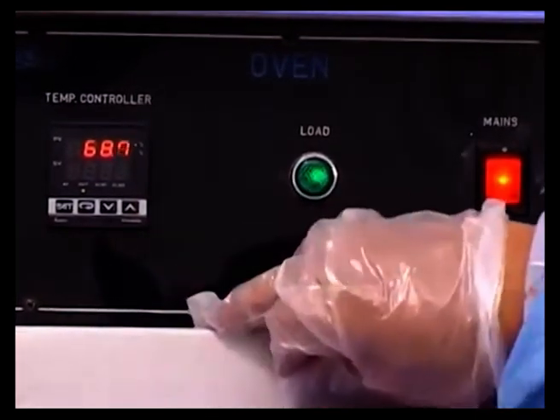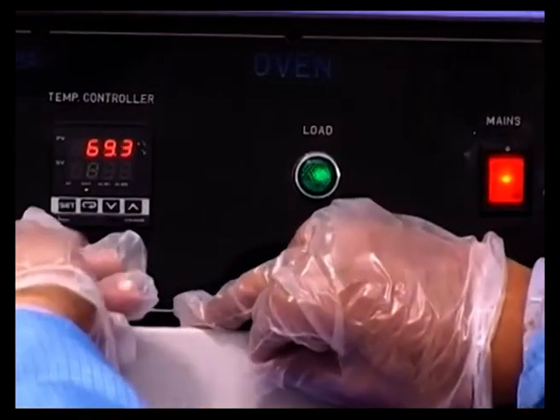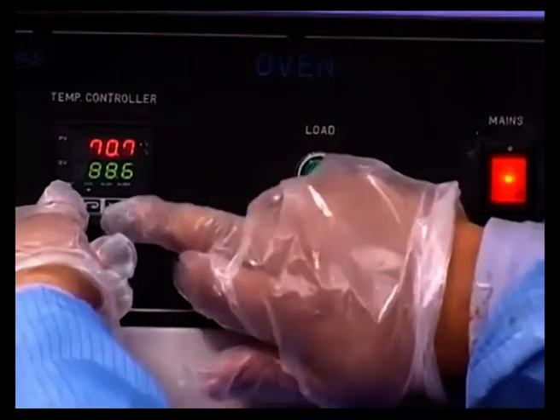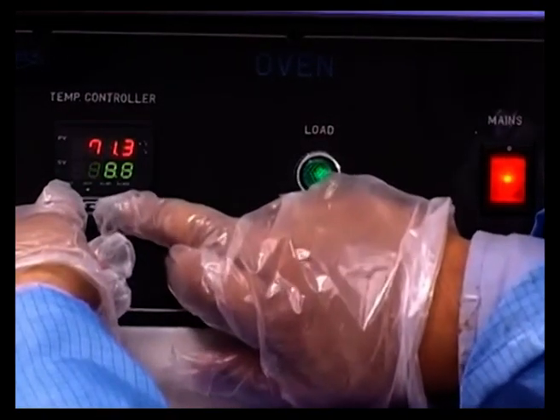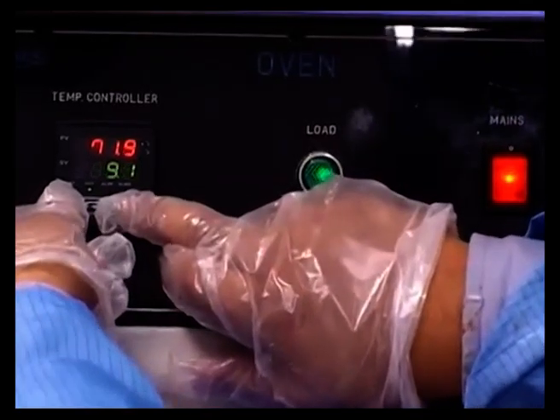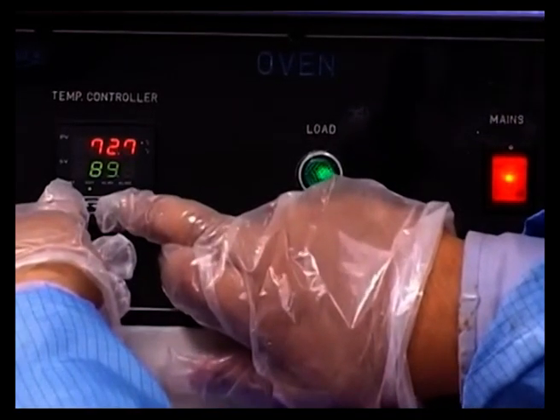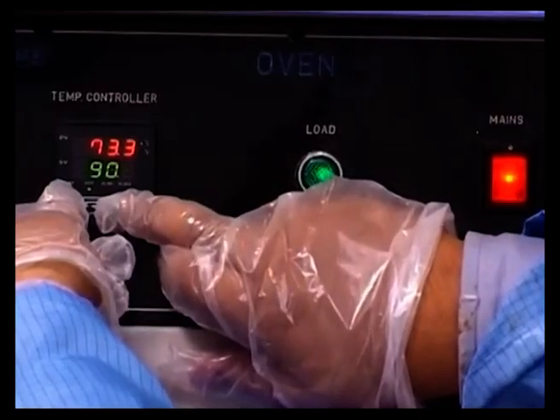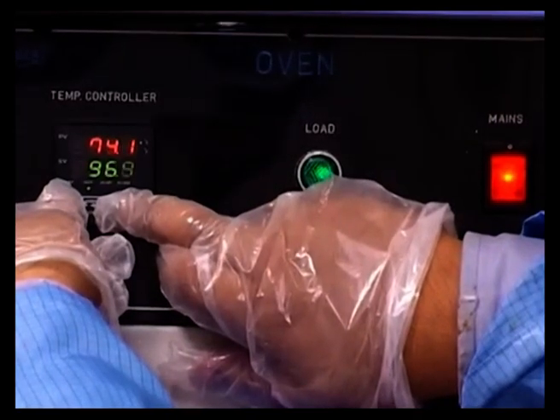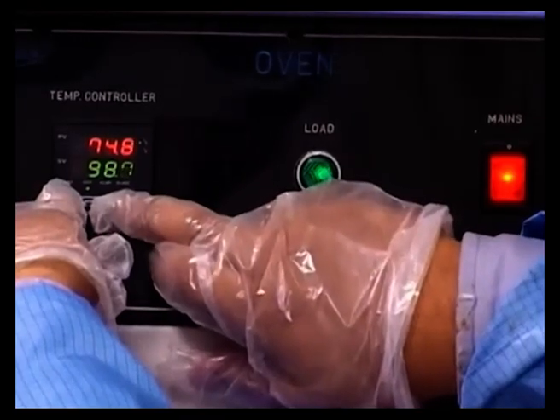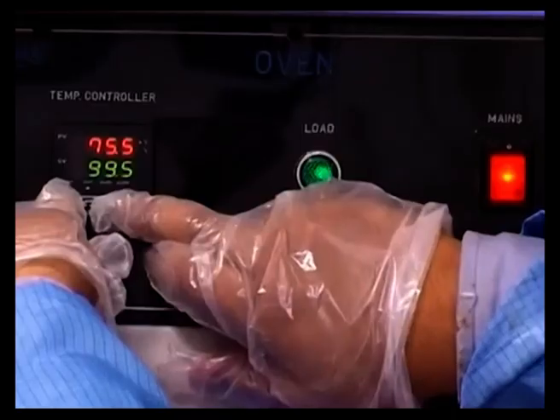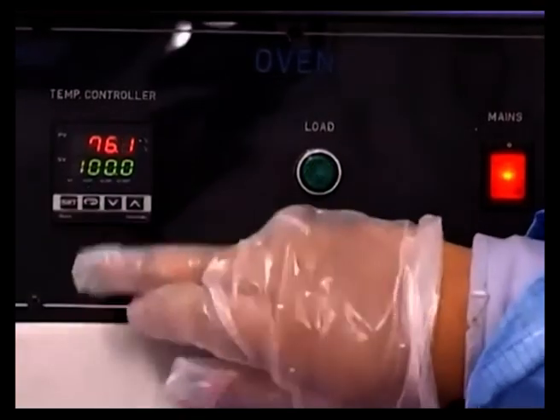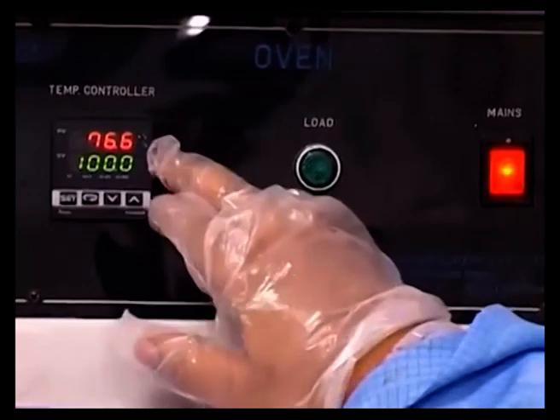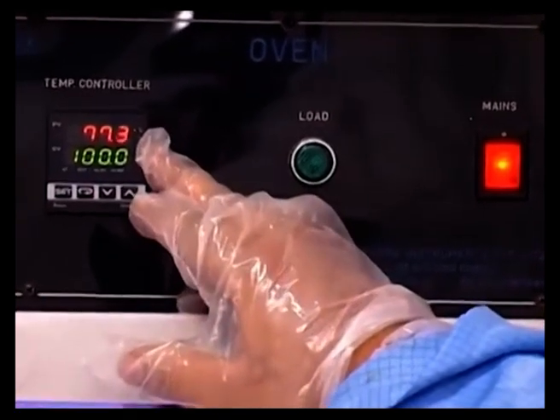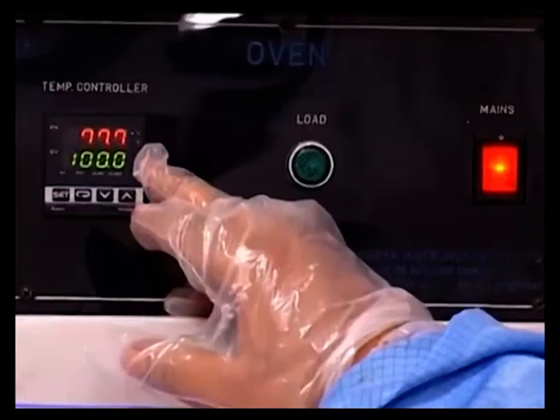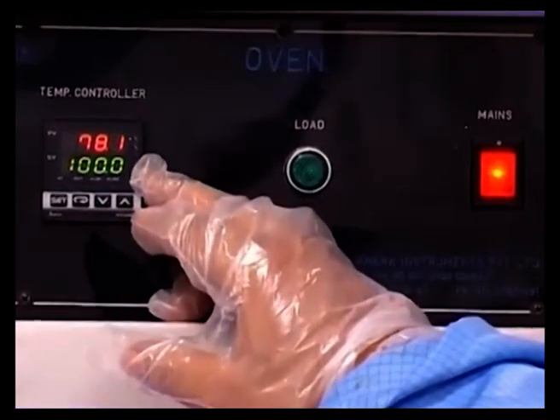In order to control this, if you can see here, there is a set option. So you press the set option and then take this up arrow or down arrow, and as you are seeing the figure here, which is the SV or the set value, is varying: 89.3, 0.4, 0.5, 0.6, and so on and so forth. So we take this all the way to about 100 degrees, which is important for proper dehydration of the wafer surface, and once you reach 100, you leave the set key, and this is now set at 100 degrees.